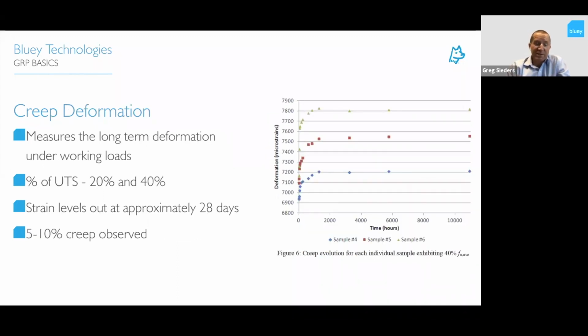So creep deformation, similar sort of testing, but it gets done to 20% and 40% of the capacity of the bar. Generally the 40% is the maximum working load we apply to the GRP bar, and 20% is probably the most common load capacity on the bar. So what we're doing here is working out what the long-term deformation of the GRP bars is under load. So you can see there in the graph, most of the deformation happens in the first 28 days. And generally about 5 to 10% of creep is observed over the time. Once it gets to load, it will then distribute out and stay stagnant on the deformation.